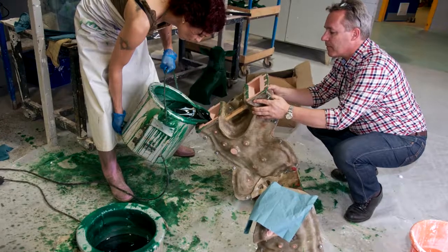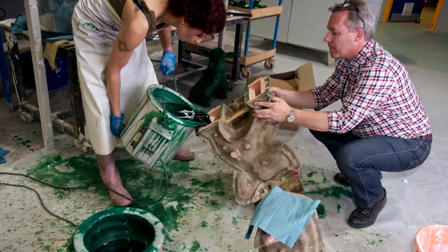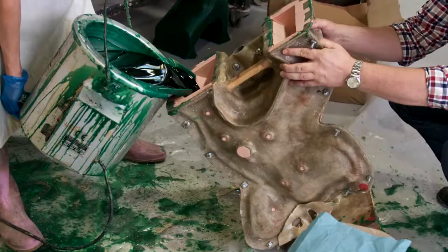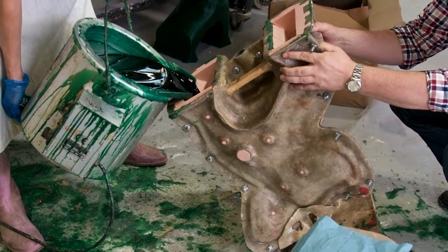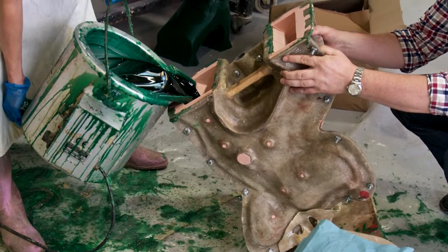The way we cast the wax is I use a 20-litre wax melting pot, so I have 2 of those. I fill in the mold, and essentially it works just like slip casting. So I fill the mold up with wax, and then I wait about 20 minutes, 25, 30 minutes, depends on the thickness that I want or the type of wax that I'm using. And then I drain all the wax out.